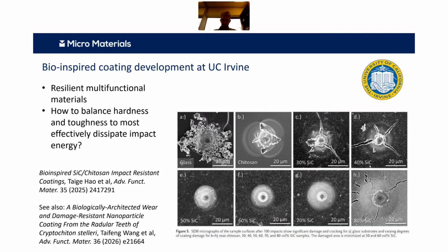And what you can see there is chitosan, there's a composite there. You put silicon carbide into that, and as you increase that fraction of silicon carbide in that composite, you rather dramatically change its impact performance, and you can see this maximum, the more localized impact damage in those cases, E and F, as you see there. So it's either those two or maybe even the G system, where you say, well, actually it's a little bit more damage, but it's no cracking. So all of that is useful information, they can understand how to build these dissipative mechanisms into their coating systems.